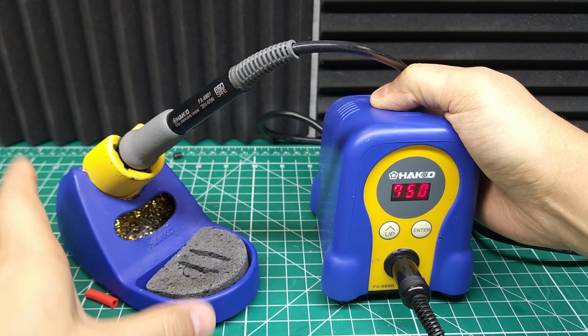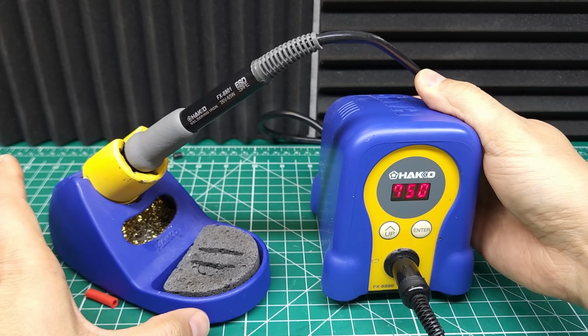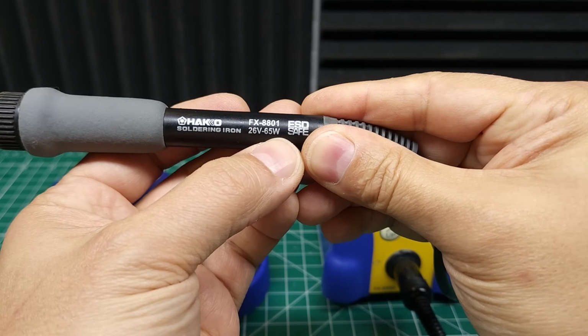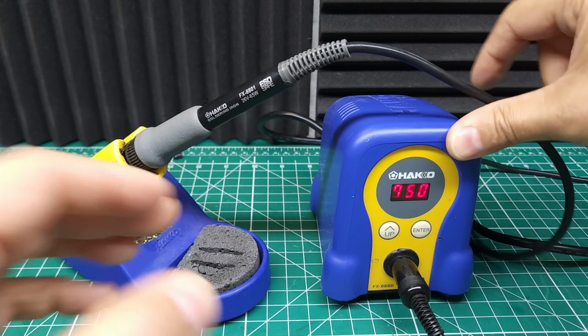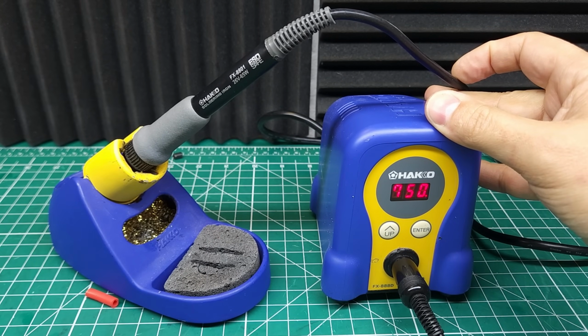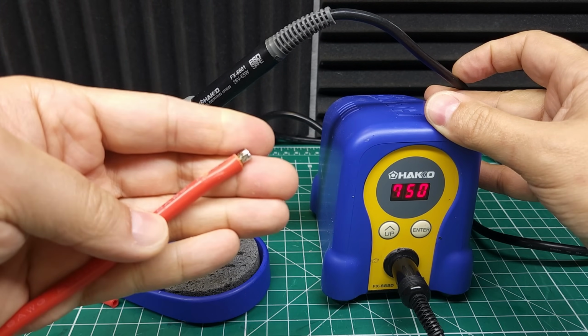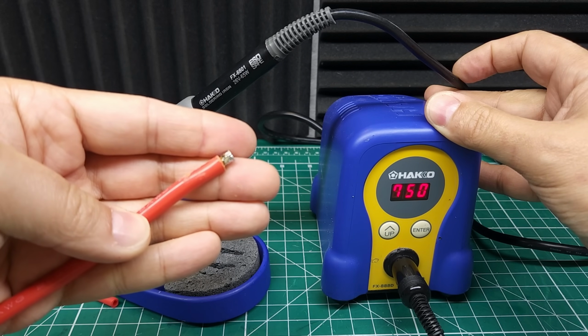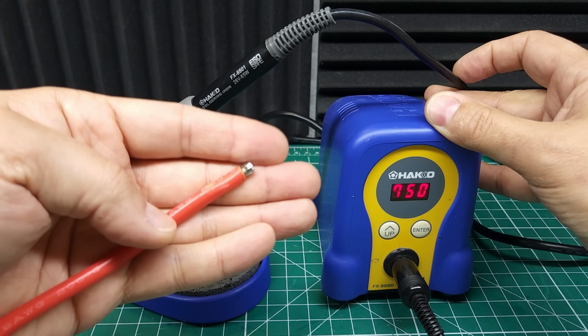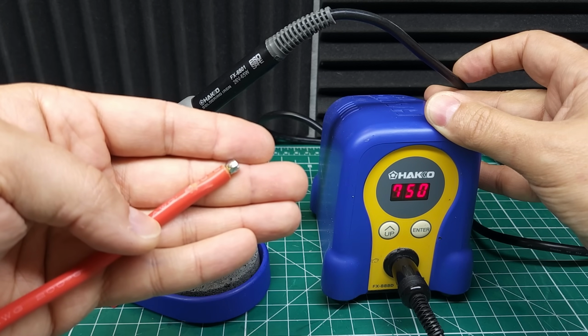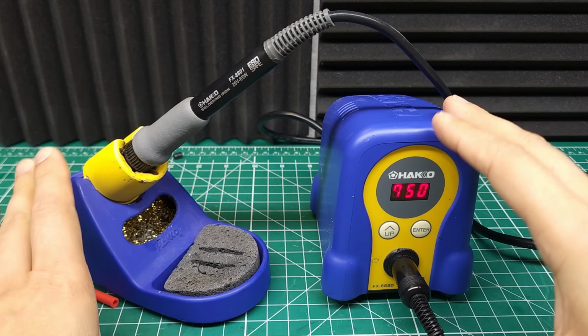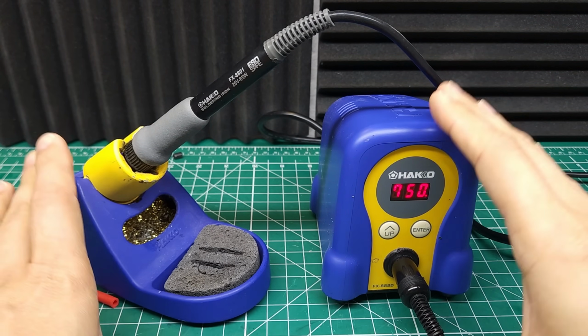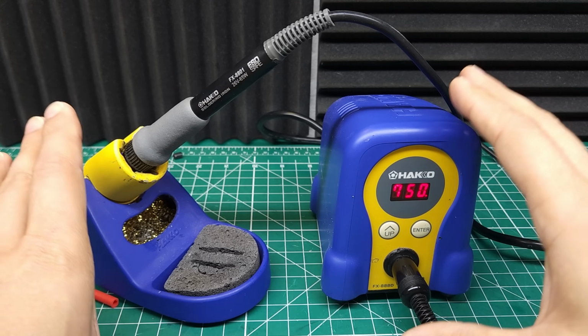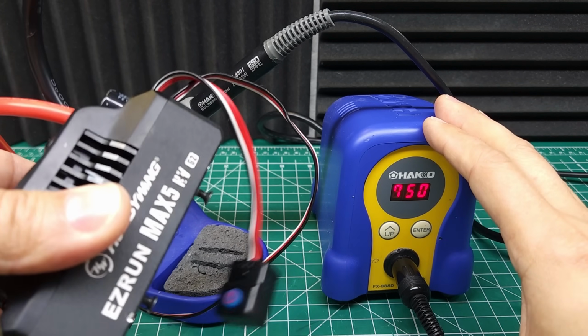And this is where the difference between temperature and thermal capacity come in. As you can see here, this is a 65-watt soldering iron, and no matter how far you crank up the temperature, the most energy it can put into these wires is that 65 watts. And if the connection you're soldering to is able to dissipate that much heat, you're never going to get a good connection. And that's why, whereas this FX888D is great for smaller wires, things like XT90s and EC5s, if you're going to be going with big power, you're going to need a soldering iron with big power.